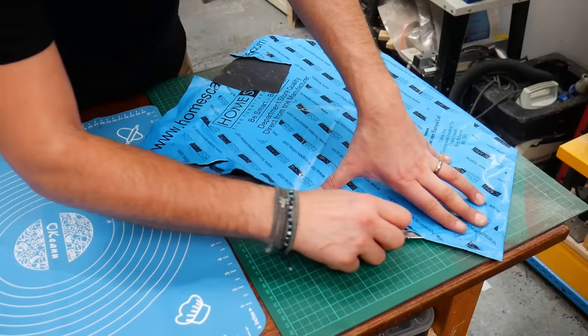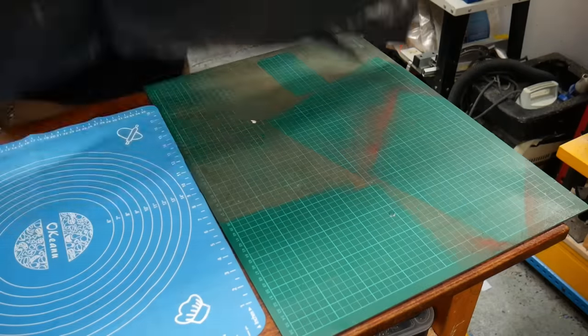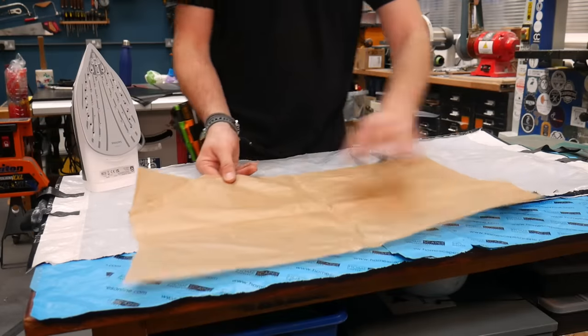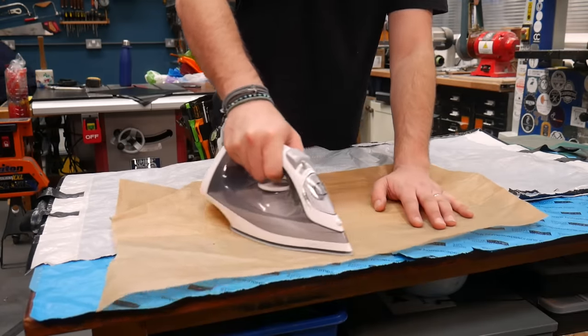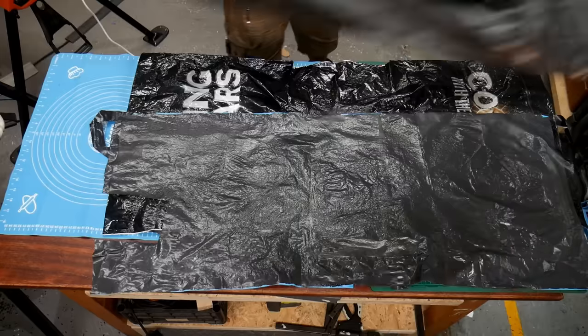We're starting off with some larger bags, which we're opening up with a knife, and then laying them flat on the workbench to give us a nice base to work from. We simply set a dry iron on its maximum temperature, and then use some teflon baking sheets or even some baking paper to protect it, and then press this down on the plastic for about 30 seconds or so. The brilliant thing about this technique is that you can just keep layering more and more bags until you hit the thickness that you're happy with.